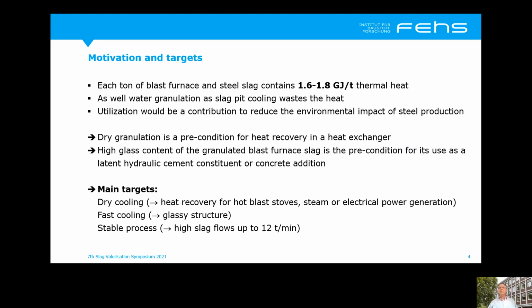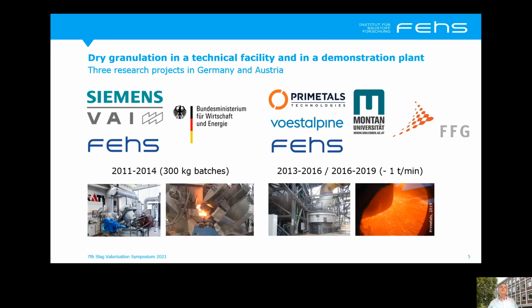Thus, we had for our projects three main targets. Dry cooling, to be able to create heat recovery, to be used for hot blast stoves, for steam or electrical power generation. Fast cooling, to achieve glassy structure. And a stable process, which is able to handle high slag flows up to 12 tons per minute at the end. In 2011, we started a first project together with Siemens.